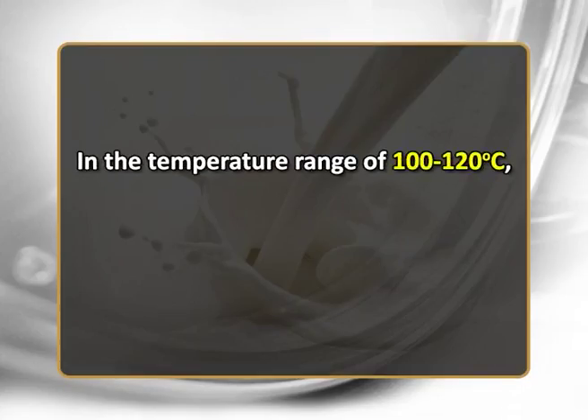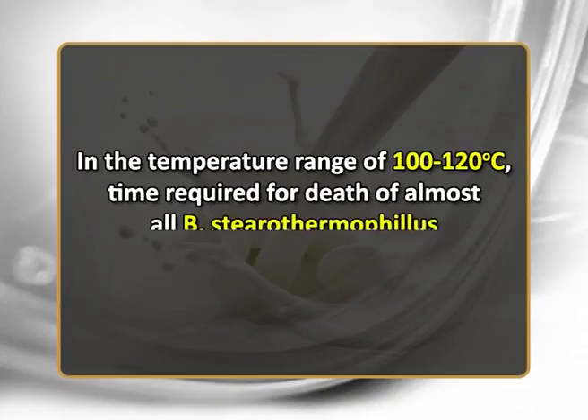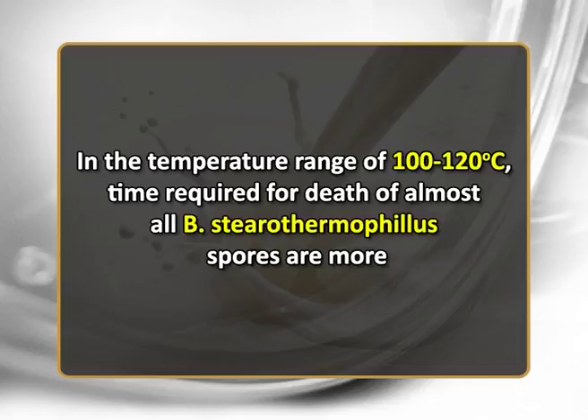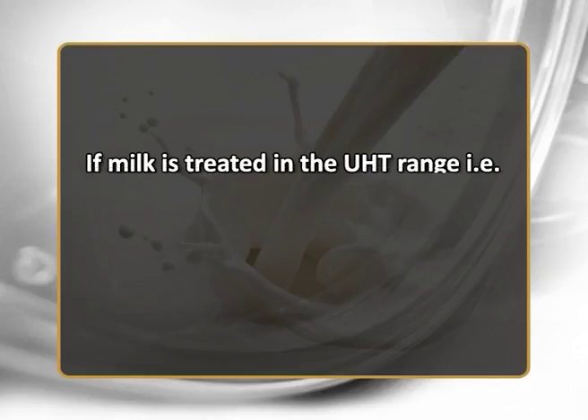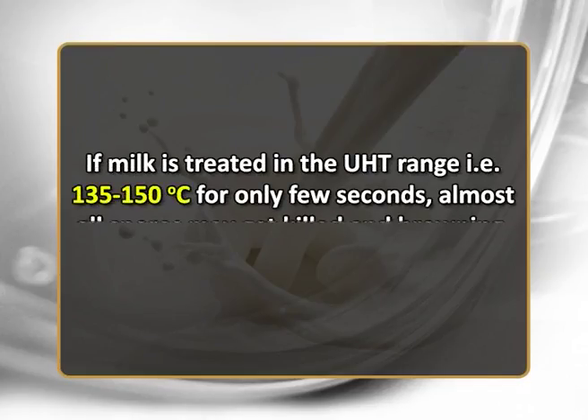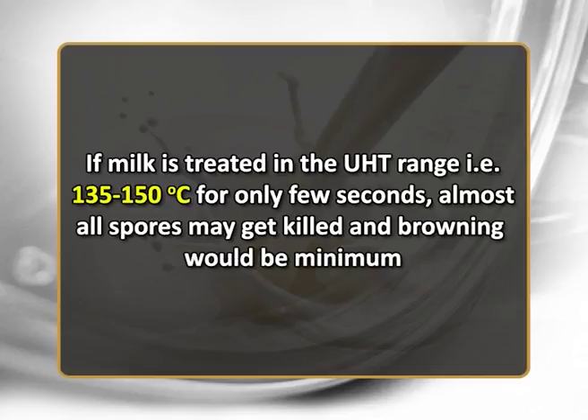In the temperature range of 100 to 120 degrees Celsius, the time required for death of almost all B. stearothermophilus spores is more. This may therefore result in more browning in the product. However, if milk is treated in the UHT range, that is 135 to 150 degrees Celsius for only a few seconds, almost all spores may get killed and browning would be minimum. Loss of nutrients and total quality also will be minimum. A product processed in this temperature range will thus be microbiologically safe and yet superior in terms of overall quality.